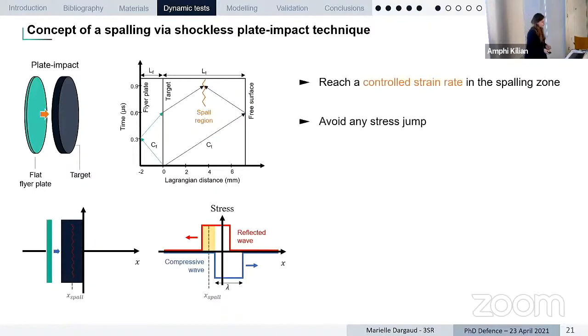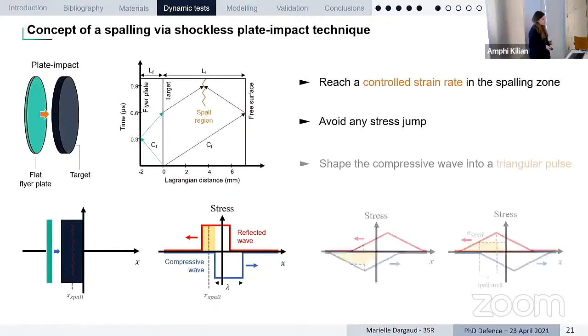So to avoid this stress jump during the overlap of the incident wave and release wave, we can actually shape the compressive wave into a triangular pulse. This way, when the triangular pulse is sent and then reflected, the overlap is going to generate a homogeneous loading rate in the failure zone of the material. We can see that we have this plateau of the superposition of the two waves, which is leading to a constant level of strain rate.